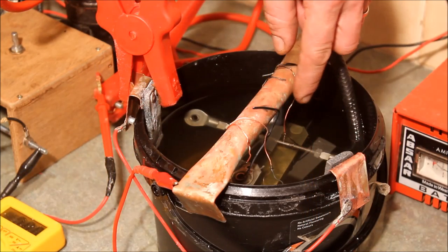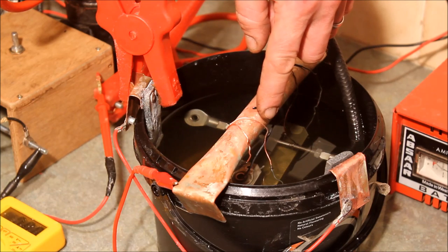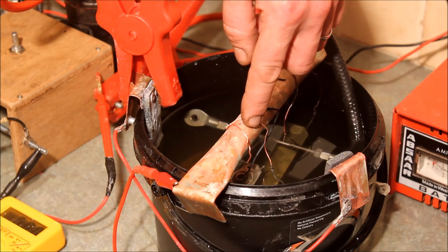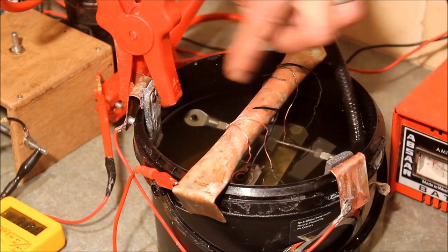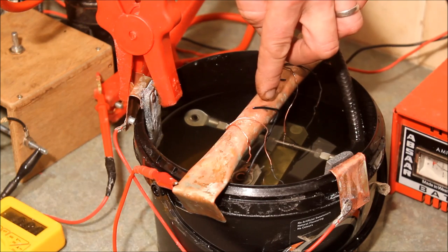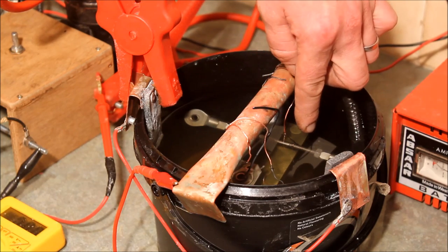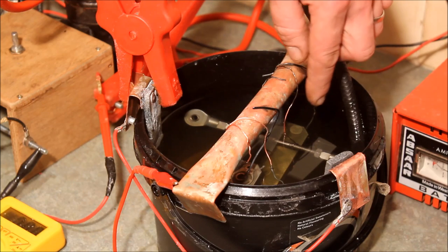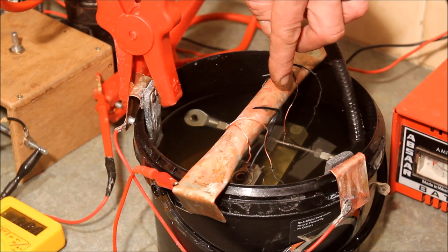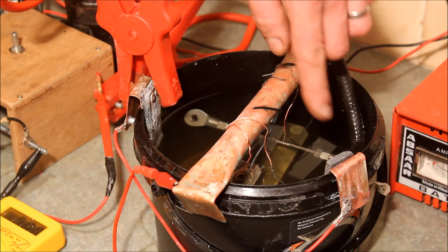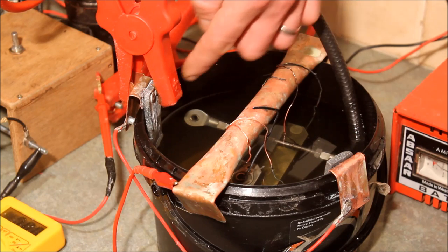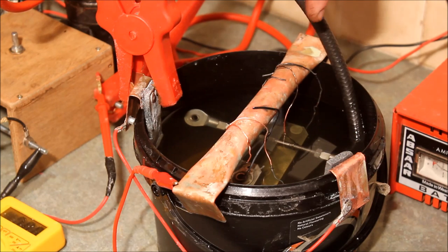And once you rinse the acid off, then put them into the electrolyte and hang them from the cathode by your wires. That's going to make the electrical contact to make the circuit all the way around. Try and hang them more or less in the middle of the electrolyte. Don't hang them in all the sediment at the bottom of the tank, and certainly don't have them sticking out of the electrolyte at the top. And then the only other thing is, make sure they're not touching the anode. You don't want them shorting out on the anode itself.